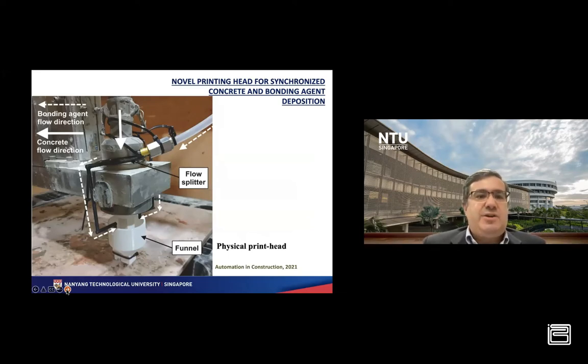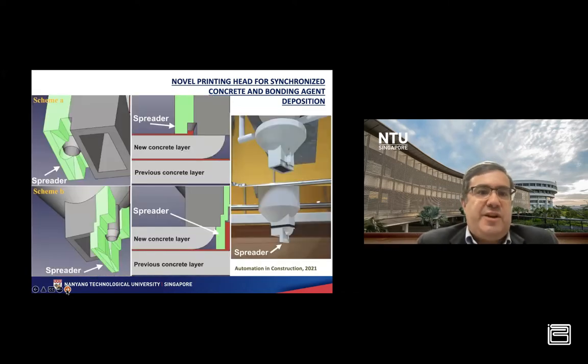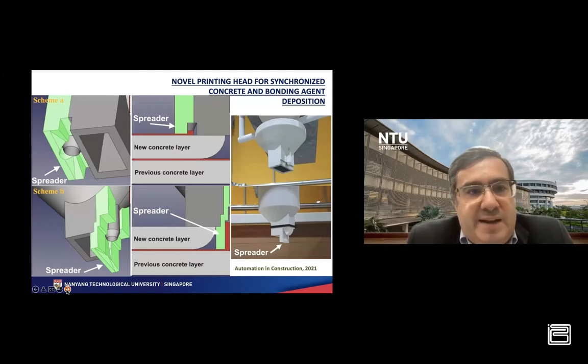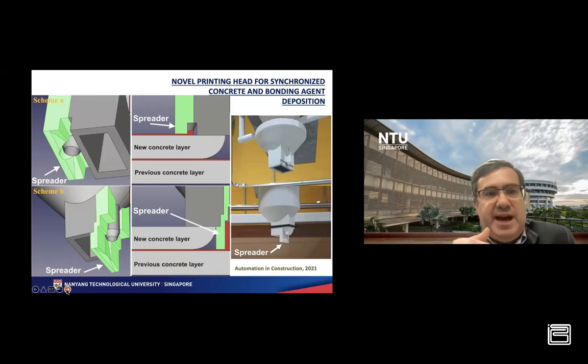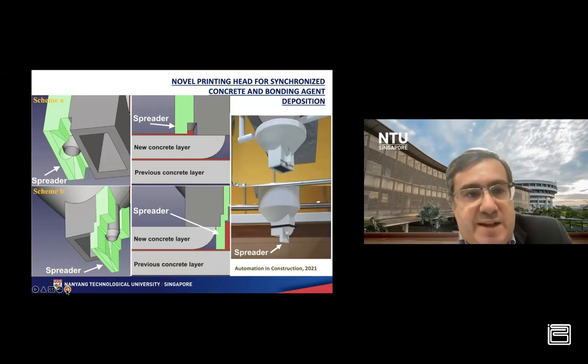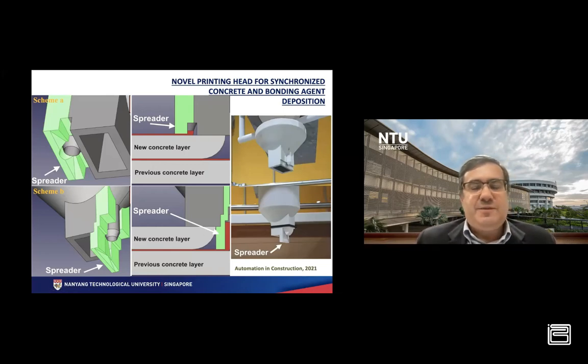Of course, we can take advantage of the pressure produced by the upper concrete layer, but nevertheless, we observe a significant number of defects. So we solved this issue by considering a spreader. And again, depending on the operation mode, we position the spreader in the right place. In the case of the first operation mode, the spreader is attached behind the bonding agent outlet, while in the case of the second operation mode, where the bonding agent outlet is in front of the concrete outlet, we attached the spreader between both outlets. And these images show the two different configurations.